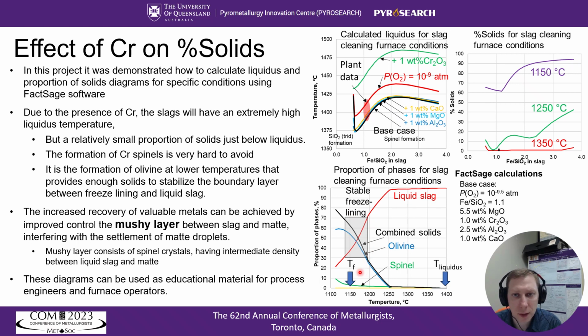The current hypothesis is that at least 50 to 70% solids in the slags are required to maintain the stagnant layer. These diagrams show that melting the last remaining droplets of spinel crystals can be very challenging. It can be more important to control the input of chromium in the slag cleaning furnace than to try to increase the temperature, if the purpose is to prevent the formation of the mushy layer. Mushy layers form on the surface between slag and matte due to the intermediate density of spinels. It interferes with the settlement of matte droplets.